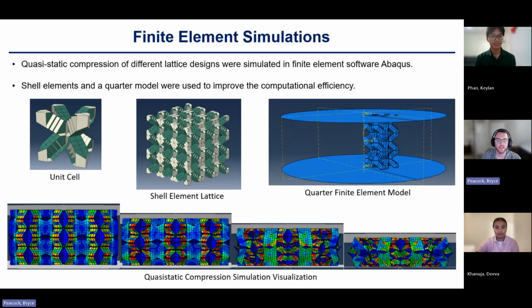For finite element simulations, we began by making I-beams with reinforcements, merging multiple instances into a unit cell. Then we patterned that unit cell into a 3x3x3 lattice. To improve computational efficiency, we used shell elements and a quarter model for the quasi-static compression simulation. For the final element simulation results, we mirrored the quarter model into the entire 3x3x3 lattice. Here at the bottom, we can see the initial point of contact of the beams and successive steps down through the second densification.